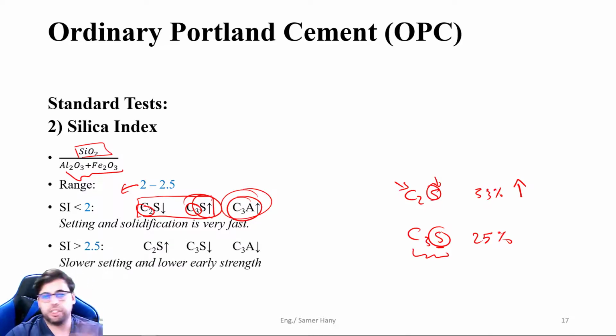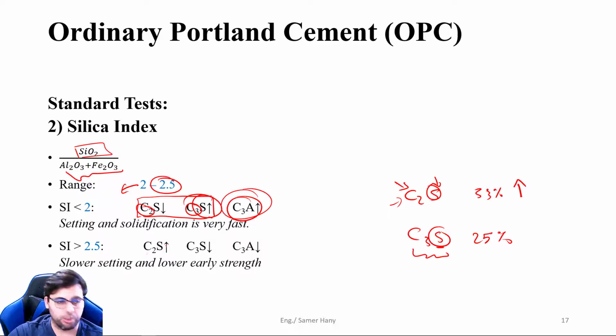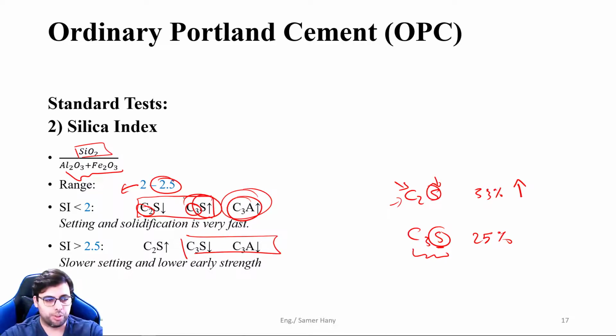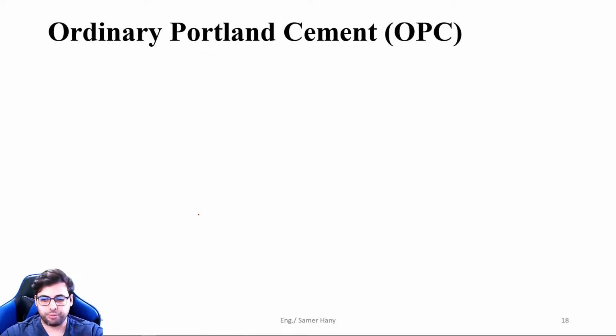Okay, and the reverse happens if the silica index falls above the maximum or exceeds the maximum limit here. So the C2S, which has higher silica content, will be formed in a higher amount than usual, and C3S and C3A will be formed in a lower amount than usual. So this indicates slower setting and lower early strength of the concrete, since C3S is lower. Okay? Alright.